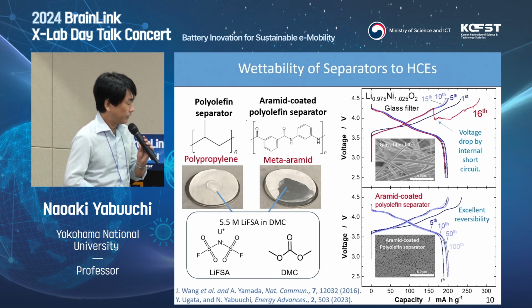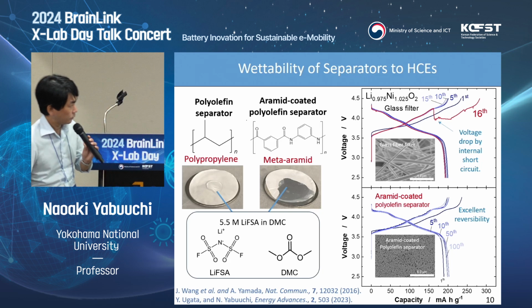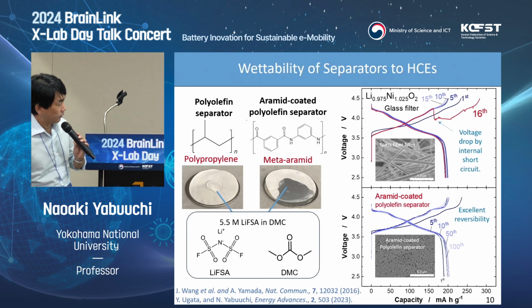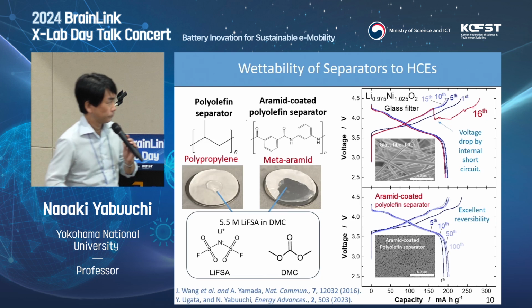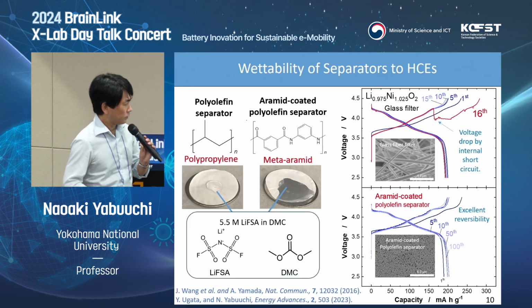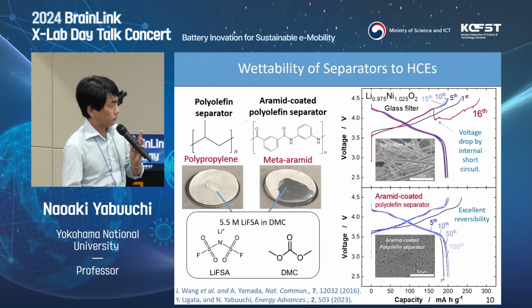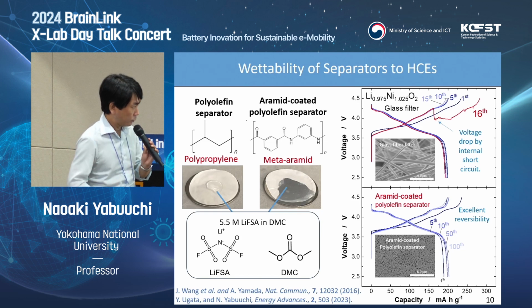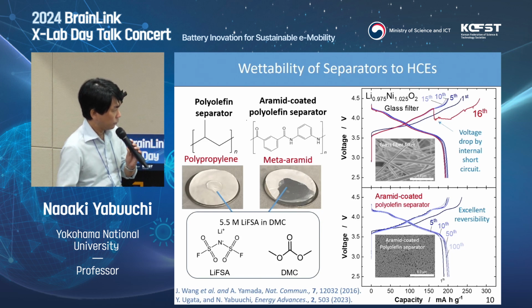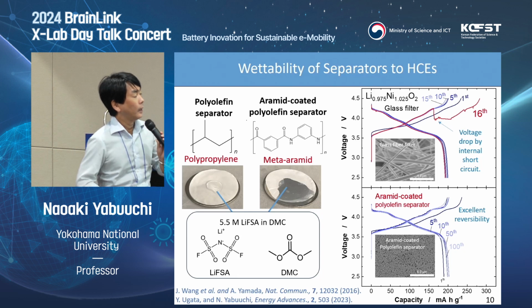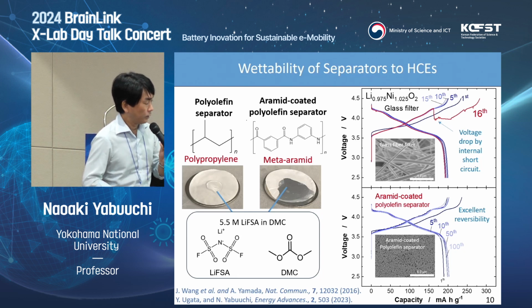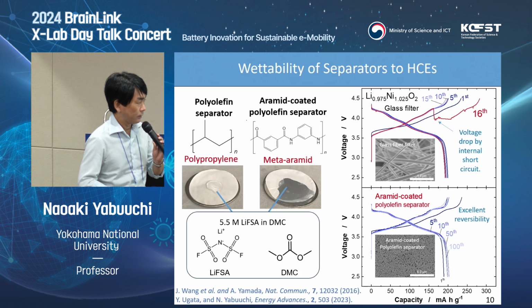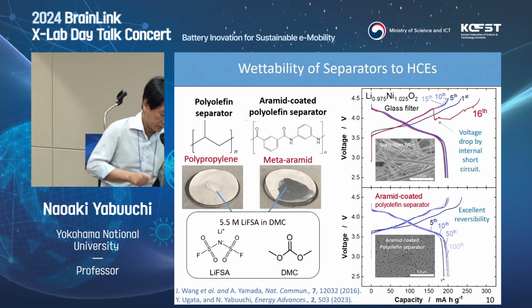The viscosity is very high. This highly concentrated electrolyte solution does not wet a conventional polyolefin separator, which has no polar functional groups. In such a case, we typically use a high-porosity glass fiber filter like this. The glass fiber filter is of course wettable by the highly concentrated, high-viscosity electrolyte solution. However, another problem is dendritic growth of metallic lithium, which results in internal short circuits.